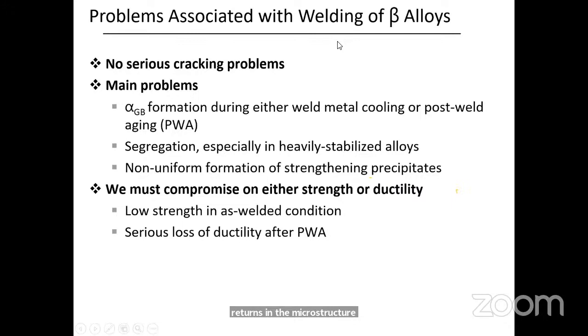Especially for these beta alloys, there are no serious cracking problems. The main problem with beta alloys is grain boundary alpha formation, which forms even during welding. Even when you do post weld aging, it still thickens and decreases the ductility. Segregation problems and non-uniform strengthening precipitates forming throughout the weld are also a problem. So you must compromise on either strength or ductility. Generally in the as-welded condition you will get low strength, but when you start aging at 500 degrees centigrade, alpha starts precipitating out, then strength will increase, but ductility will drastically decrease.